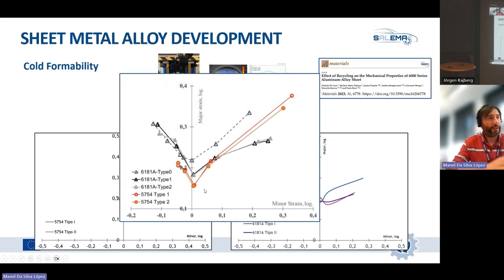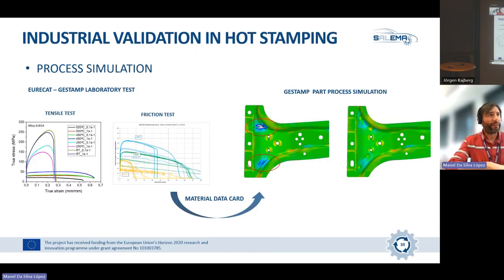But even if they exhibit worse formability, if we put all together in one single chart, we can see that these new 6181 alloy variants have a close formability to the 5754. So not big trouble or not big loss of formability. So we can still deal with them and work with these alloys,